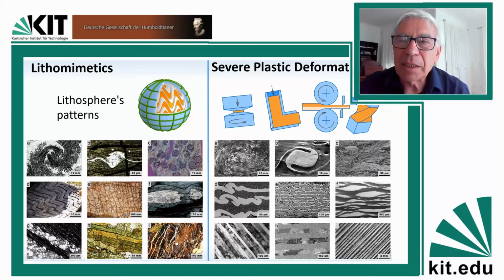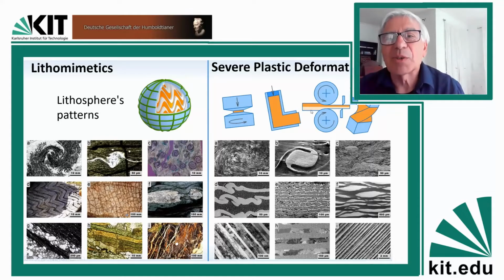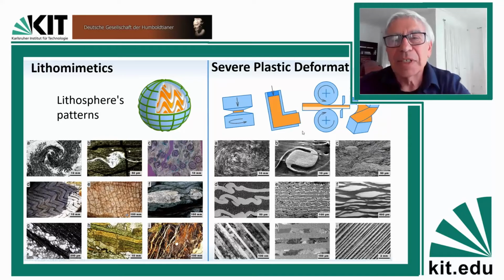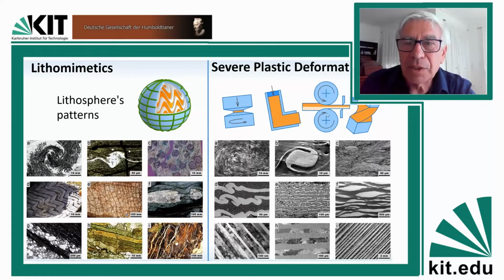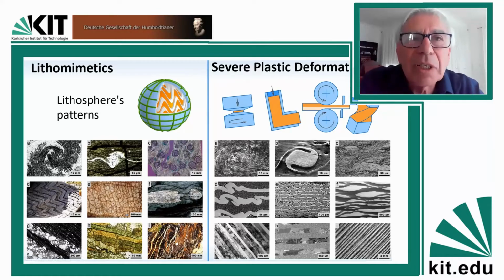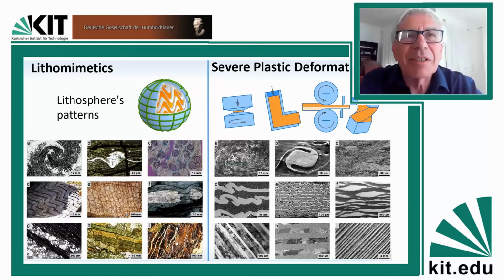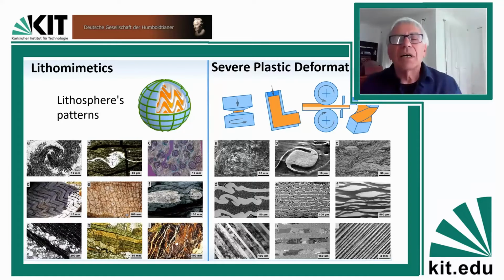There are some other techniques like equal channel angular pressing, where you push a billet through an L-shaped channel. It comes out with the same cross-sectional dimensions so that you can repeat the process. You put the billet again and again and again into this die, and again you accumulate very large deformations. There are some other techniques like this one, the asymmetric rolling, where you can also produce large shear deformations. The twist extrusion technique, pushing a billet through this complex twisted channel of the die, you can produce, again, very high strength and very small grain size.